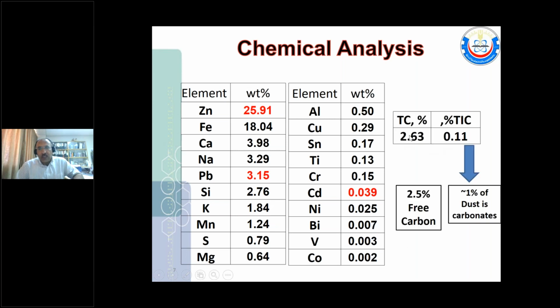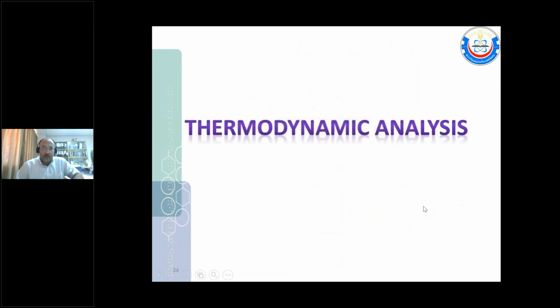Additionally, we did total carbon and total inorganic carbon, and we calculated that we have in this dust about 1% of carbonates and 2.5% of free carbon.